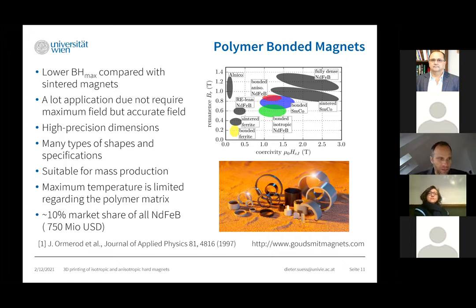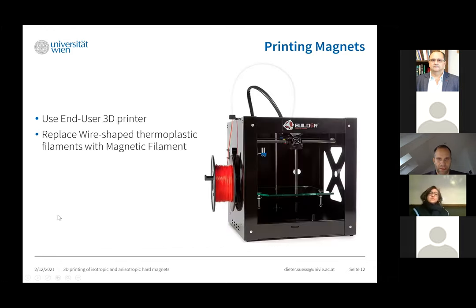With fused filament fabrication, you can only produce polymer bonded magnets. Anyway, polymer bonded magnets are a huge market for high performance magnets. If you think about sensor applications where you need a very accurate field, but not a very high field strength, and high flexibility in the shape of the magnet to realize this particular field, polymer bonded magnets are the best choice. And about 10% of all neodymium iron boron magnets on the market are polymer bonded magnets.